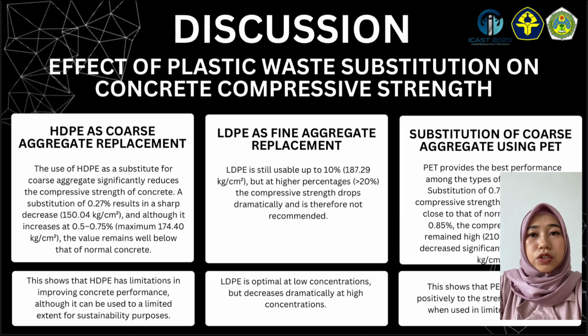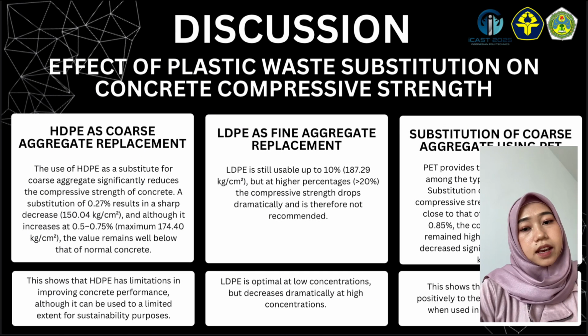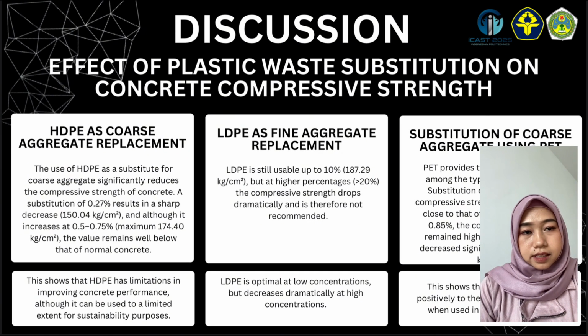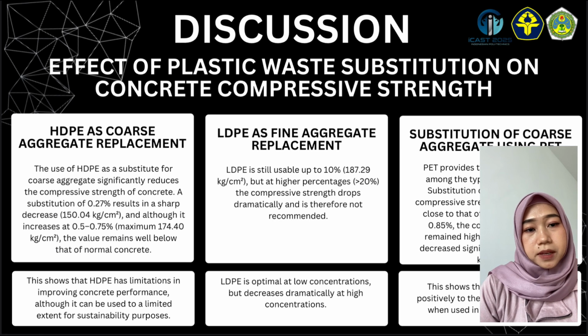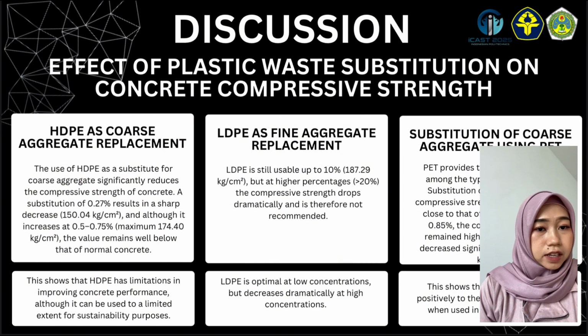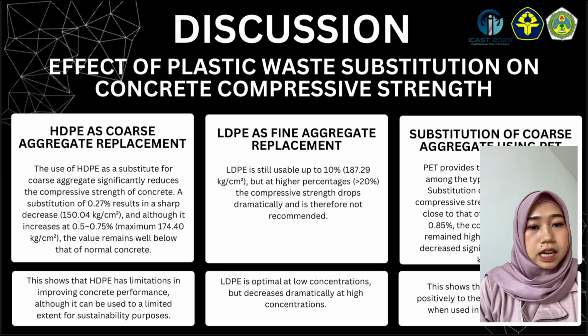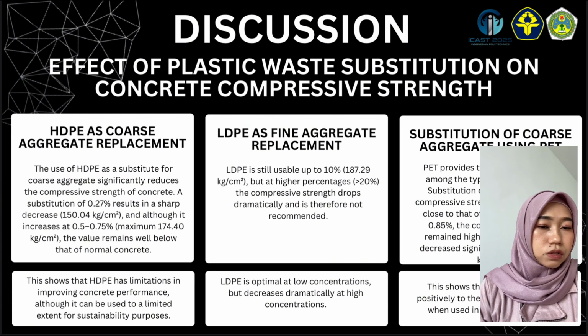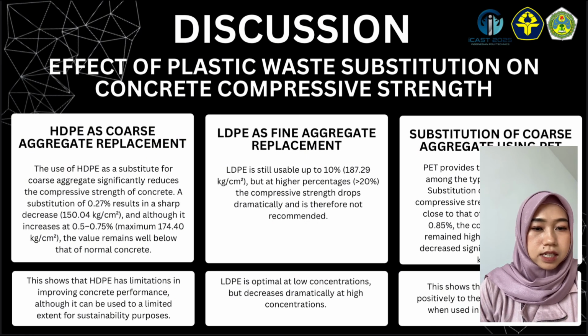Discussion. Part 1. Effect of plastic waste substitution on concrete compressive strength. First, let us discuss the effect of different plastic waste substitution on compressive strength. HDPE as coarse aggregate replacement. The use of HDPE as a substitute for coarse aggregate significantly reduced the compressive strength of concrete. A substitution of 0.27% results in a sharp decrease, and although it increases at 0.5 to 0.75%, the value remains well below that of normal concrete.